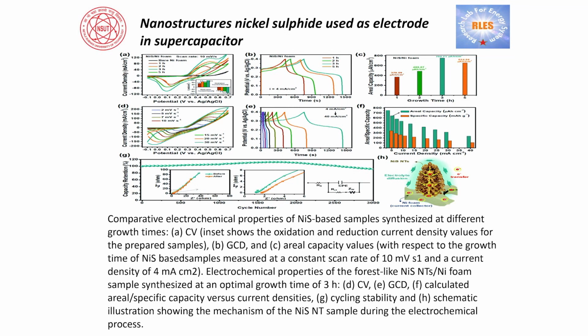samples, measured at a constant scan rate of 10 millivolt per second and a current density of 4 milliampere per centimeter square. Electrochemical properties of the forest-like NiS NT, Ni foam sample synthesized at an optimal growth time of 3 hours: CV and GCD, calculated areal specific capacity versus current densities, cycling stability, and a schematic illustration showing the mechanism of the NiS NT sample during the electrochemical process.